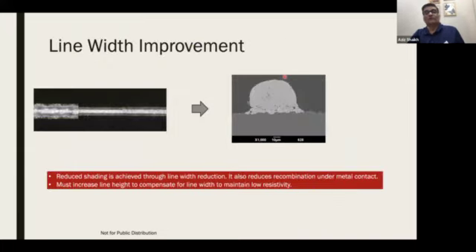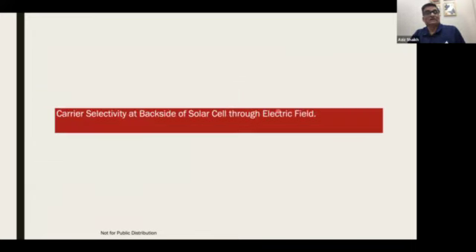The other thing going on in the industry is, as I was telling you, wherever these silver lines are, the light cannot penetrate those silver lines. So initially the technology had very wide silver lines. Now the improvement has been to make these silver lines narrower. Today it is even better than this. I'm showing 50 microns or so here, and today we are down to 29 microns, 28 microns, etc.